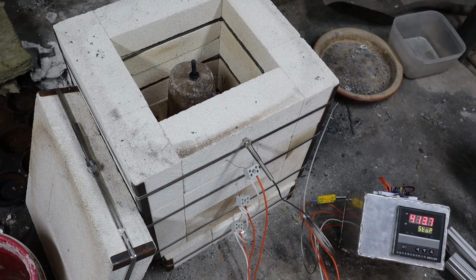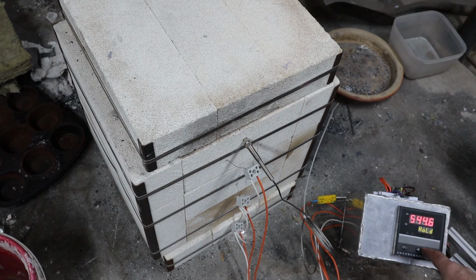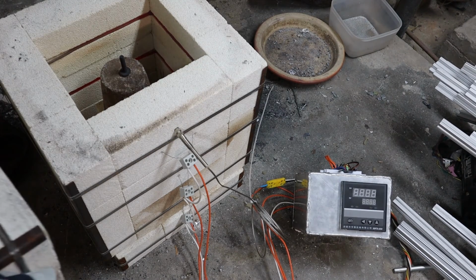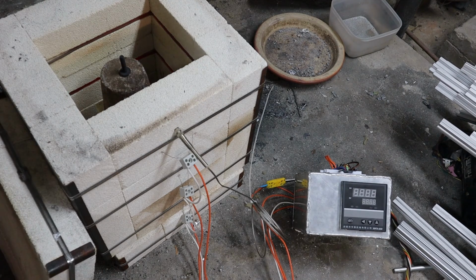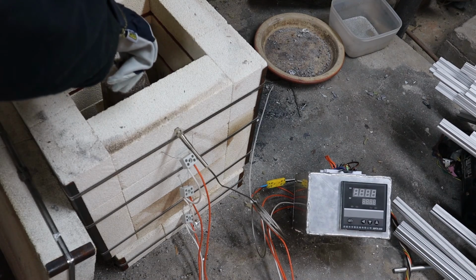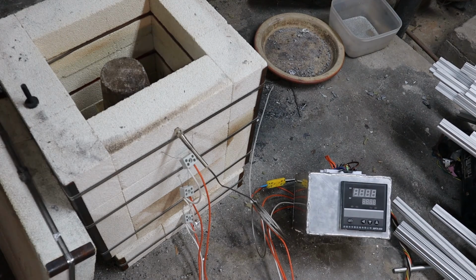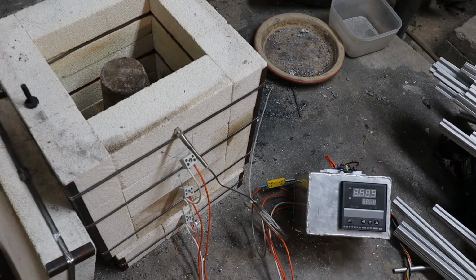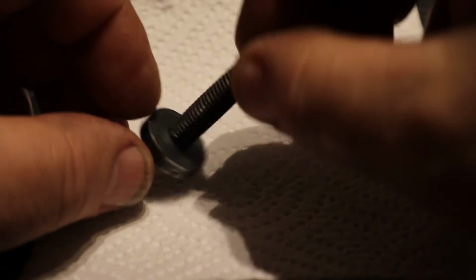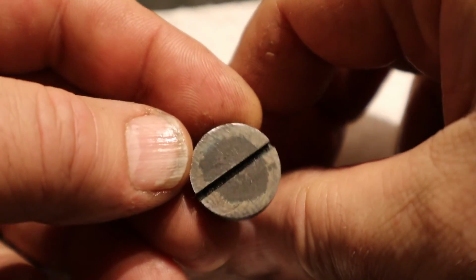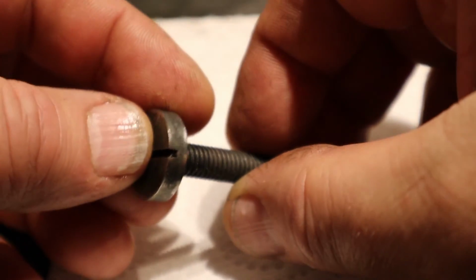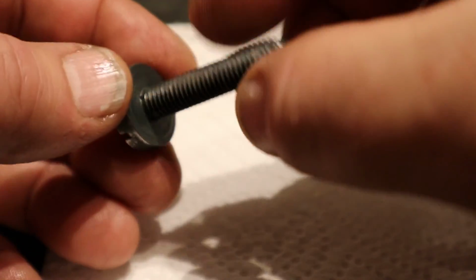Immediately followed by tempering at 600 degrees for an hour. I think this is called tough tempering. And here is the result. It isn't really soft anymore, but a file will bite into the surface.